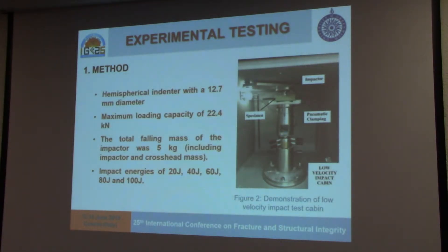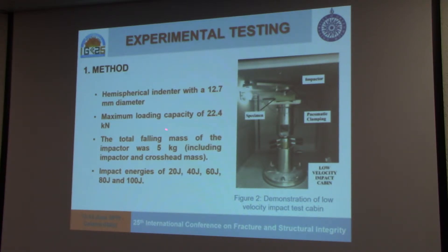For the tests, we used an Instron impact test machine. The indenter was the hemispherical one with a diameter of 12.7 mm, and the maximum loading capacity of the machine was 22.4 kN. The impact energies were five different levels starting from 20 joules to 100 joules.